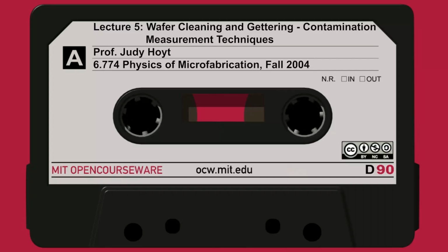But it's pretty darn good compared to any other semiconductor oxide insulator system. So as a result, the defect densities at the interface that we measure are in the range of 10 to the 9th to 10 to the 11th defects per square centimeter. Remember, the surface atom density is about 10 to the 15th. So again, it's about 1 in 10 to the 5th, something like that.